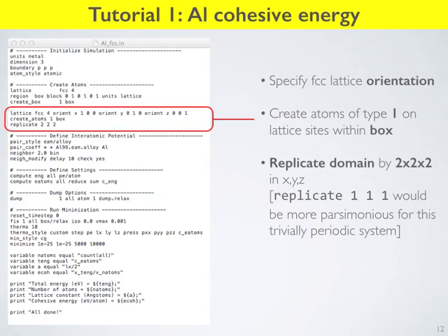So sometimes it can be interesting to simulate a bigger system. Typically, one of the convergence checks you might want to do for your simulation is, do my answers change as I change the size of my system? Because you want to be sure you're simulating a big enough fundamental simulation cell that your answers aren't dependent on your system size. So an easy way to do that might be to add this line and write a bash script to go in and change that line and make your system bigger and bigger and rerun your simulation and check your results. Very similar to what you did with your K-point sampling in Quantum Espresso. But the simulation would run fine if you just replicated 1, 1, 1 or ignored that line completely. So just a little subtlety, but it does speak to a more advanced functionality that you could build a script to run on top of it.